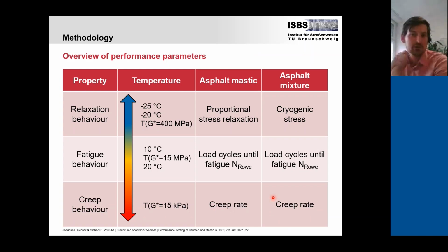Now, for each of the different temperature ranges, we have a specific material property which we are looking at, and now we can compare the performance parameters which we defined and determined. So in the low temperature range, we have the proportional stress relaxation as the performance parameter, which we can compare to the cryogenic stress of the asphalt mixture. In the intermediate temperature range, we have the load cycles until failure for both material scales. And in the high temperature range, we look at the creep rate.